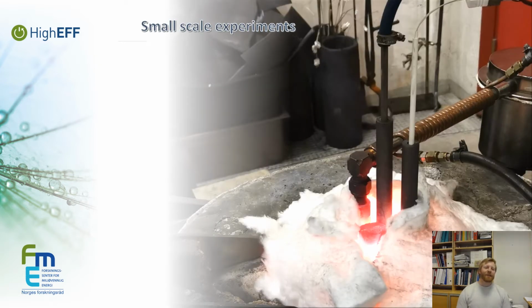We are also working on developing a small-scale experimental setup to look at SiO combustion in different atmospheres. So here is a very simple setup in an induction furnace where we generate the SiO gas and let it combust in different atmospheres. And then we collect the byproducts in a filtration system and look at how different atmospheres affect this process.